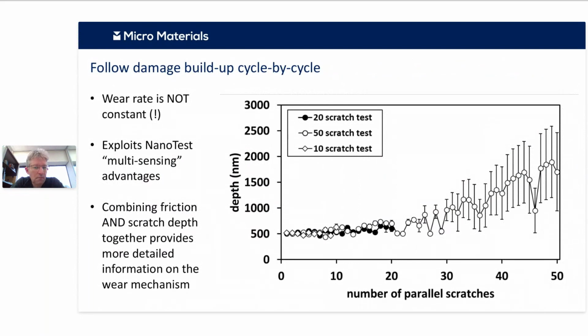So that's all pictures of the surface, but actually what we can do is we can track the deformations cycle by cycle within the test. And this, we can track the deformation along the entire track. We can look at mean values on those tracks, and we can then look and see how those mean values change as a function of cycles. In this case, is an example where up to about 20 cycles, this surface is essentially quite resistant to failure, but then after somewhere around 20-25 cycles, you're getting a transition to a more abrupt damage regime, essentially.